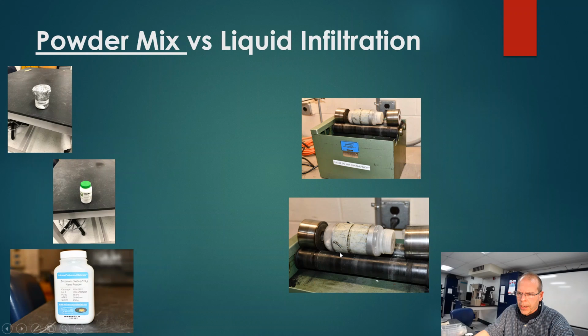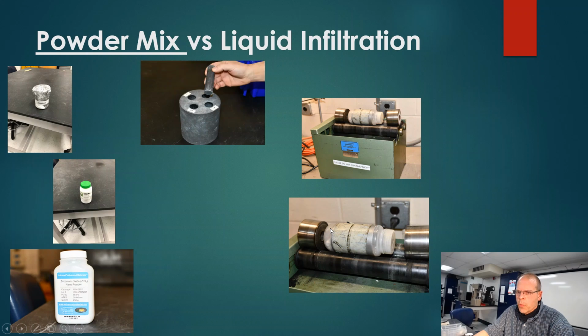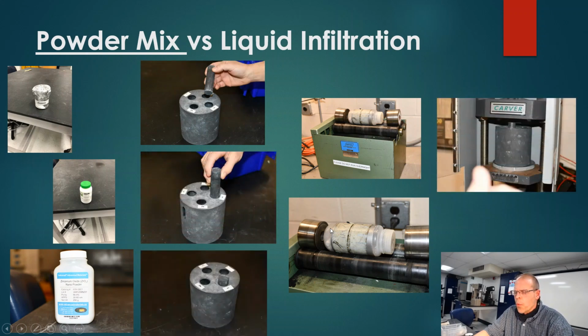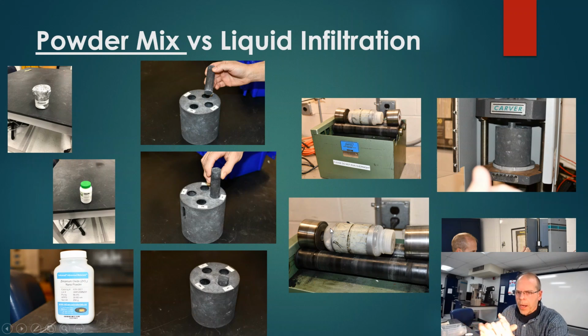You'll see this in a short video. I have little ceramic cylinders in here, which are going to help mix the powders together. And when we're done, we're going to go back to the graphite mold and we'll press this stuff together. And so I'm going to actually end up making a puck, not just of aluminum oxide, but of aluminum oxide and the zirconium oxide mixed together. That's one of the models that we are going to make for powder mix.